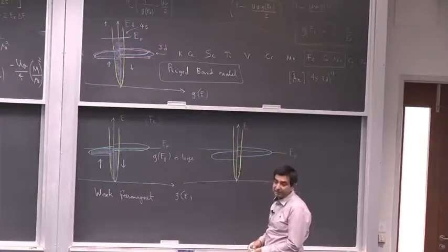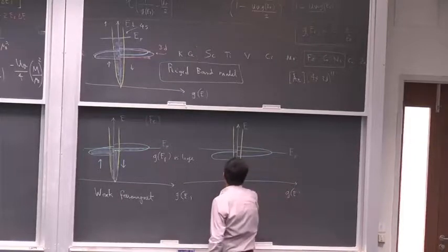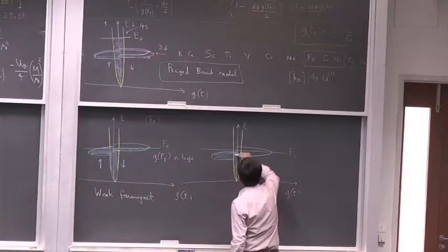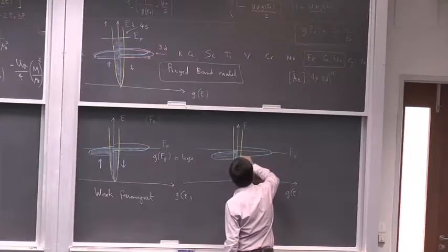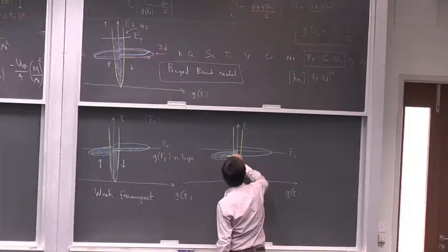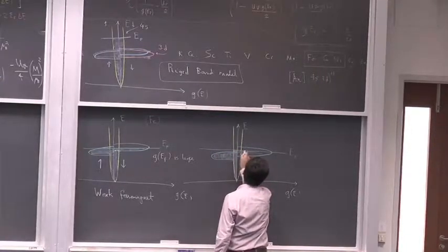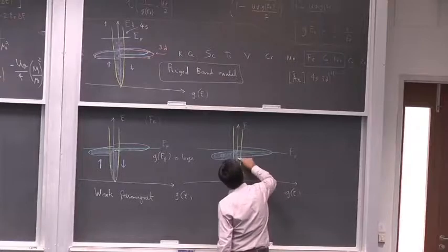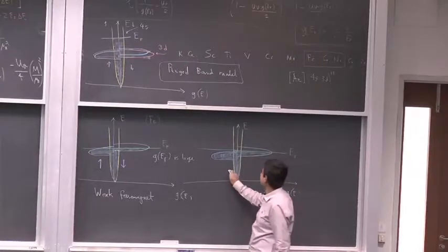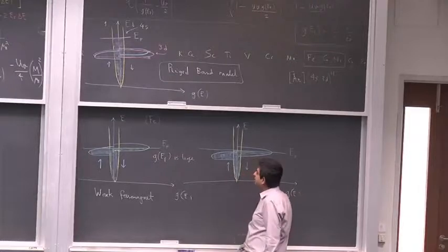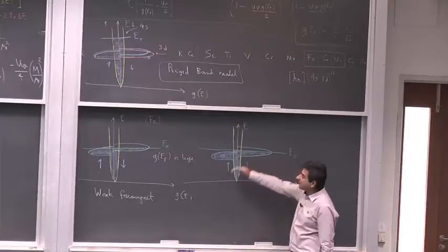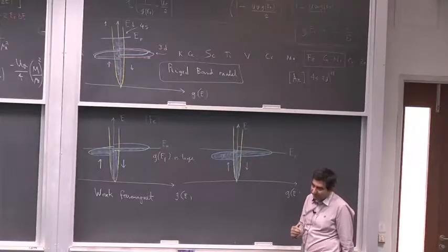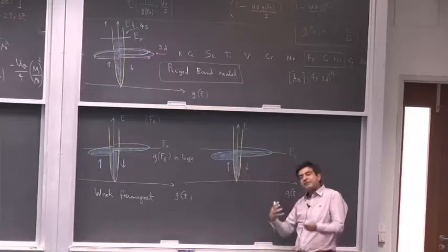Once again the sample gets magnetized, because there is a higher preponderance of electrons of the majority spin and a fewer number of electrons which are the minority spin. Now what's happened is that the position of the Fermi level is such that it's still intersecting the 3d band, so we expect that the Stoner criterion may be satisfied for this material. And now one of the bands, the majority spin band, is completely filled.